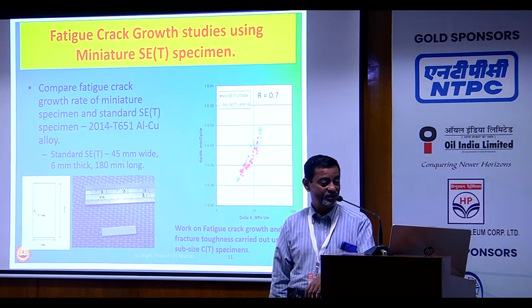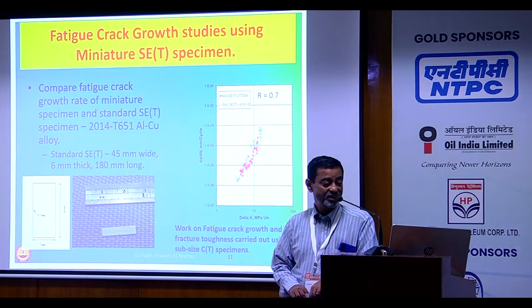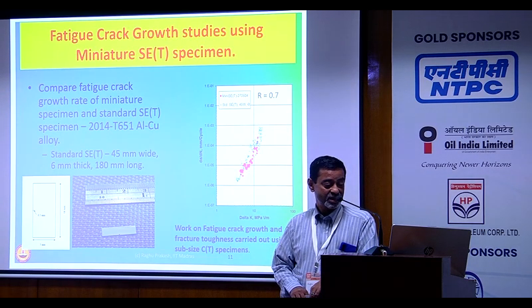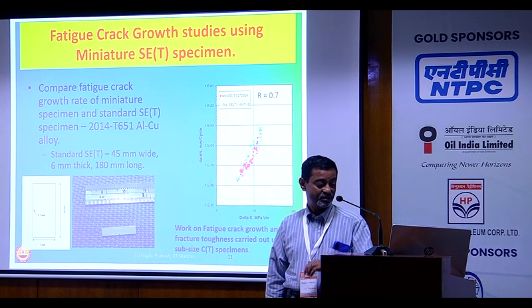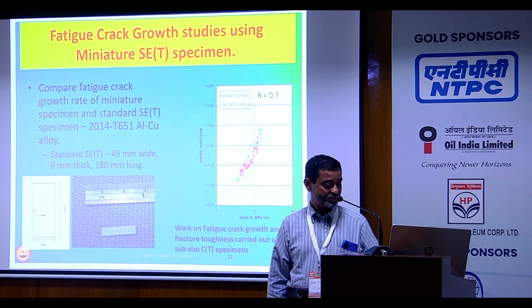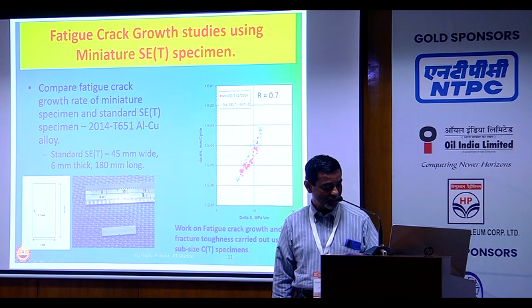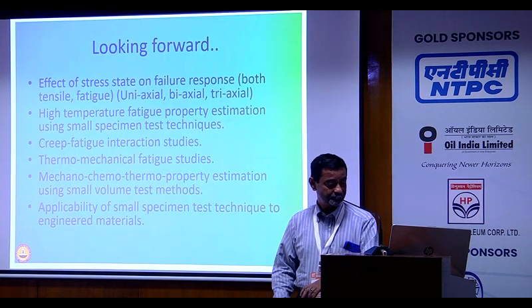And apart from that, we also did some crack growth studies using miniature samples. You can see in the graph on the right-hand side the data from miniature samples, as small as what you see on the left, 15 mm by 5 mm by 0.5 mm thickness, and the data compared with what you get with a standard specimen. So these are the other work that we are looking at.